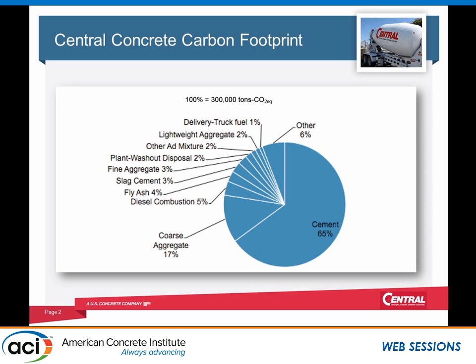One is to increase the amount of fly ash and slag that we're using, which is a good way to do it. Another way is to take a look at the specification and realize that a lot of what we're doing in terms of concrete placements is grossly over-designed. So what I tell all of our project managers is take a look at the specification and see what it is that they're trying to get at, and let's submit that first. It's probably going to get rejected, and at that point, that's when I can go in and have a conversation with the engineer of what it is that they actually need. A lot of our structures are vastly over-designed for the amount of cement that we're putting in it.